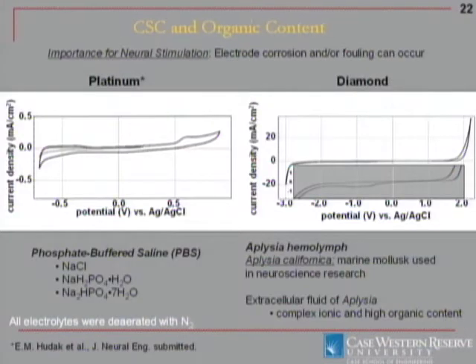But when you go to an electrolyte that has a significant amount of proteins, we've done a few different electrolytes. One of those is actual hemolymph from the Aplysia californica from Hillel Chiel's lab here in biology. This is the extracellular fluid and also the blood of the animal, so a lot of proteins present. If we compare that to phosphate buffered saline that just has ionic content, the voltammogram is a lot different for platinum. We lose a lot of that activity for hydrogen adsorption. The amount of current overall is down. And so that will affect how charge transfer and this charge injection would occur.